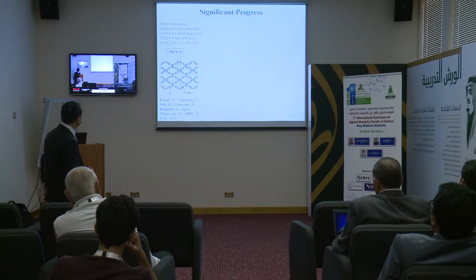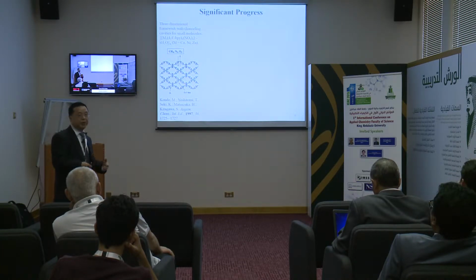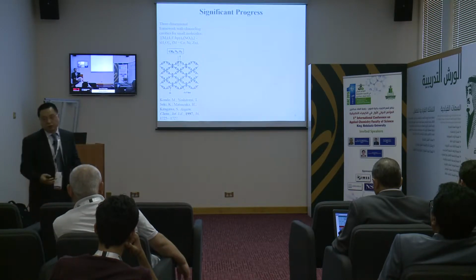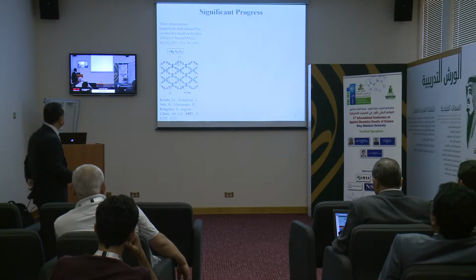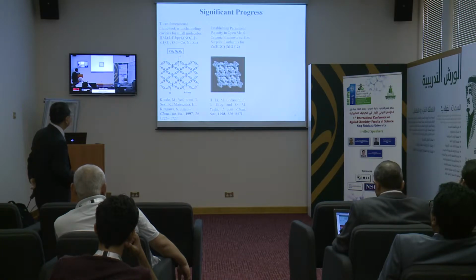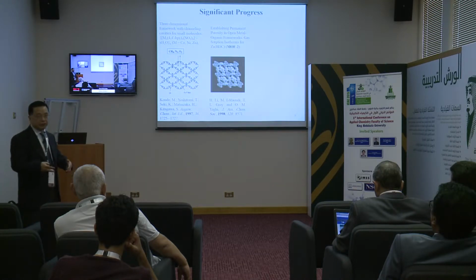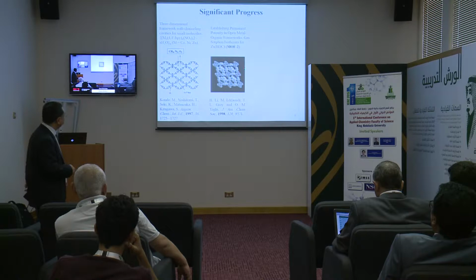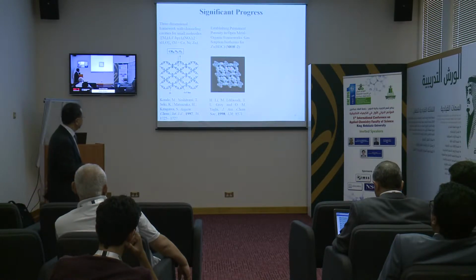This is one example. The structure is two-dimensional, but here the absorption has to be realized under very high pressure, because the uptake is very, very low, but still it's quite important progress. And this is very important. So Mohammed here made the most important contribution to establish this permanent porosity. This structure is two-dimensional, and it is a very important structure, although the porosity here is about 500 square meters per gram.